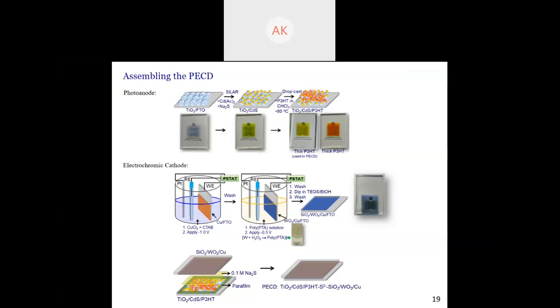Next is the electrochromic cathode. I have electrodeposited a very thin copper layer from a copper salt, washed it, and then again went for electrodeposition of a WO3 layer with a polyperoxotungstic acid solution, and then annealed it. You can see the color of that.